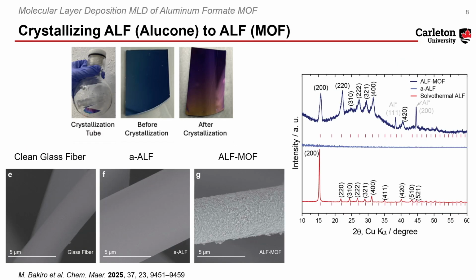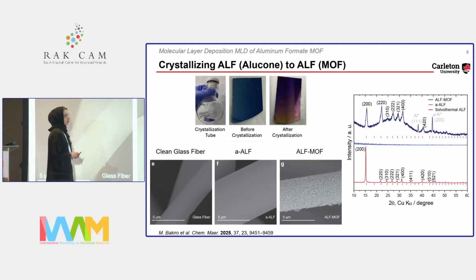And then, for the as-deposited film, we try to see if it's crystalline. You see this line here. It's not a line I drew, it's just the XRD. It's just very flat. It was not crystalline as deposited. And we thought maybe the signal is not very intense. So we tried to deposit it on glass fiber to increase the surface area and make it easier to handle as a thin film. And it was not crystalline.